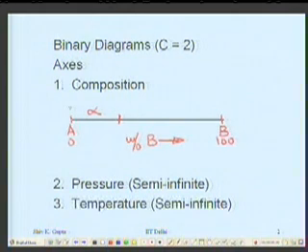And the beta phase, the second phase, exists from 80% B to 100% B. Where 0% to 30% alpha is existing, beta cannot exist because that's the equilibrium. Where beta exists in equilibrium, alpha cannot exist. Maybe in between 30 and 80, both of them exist.